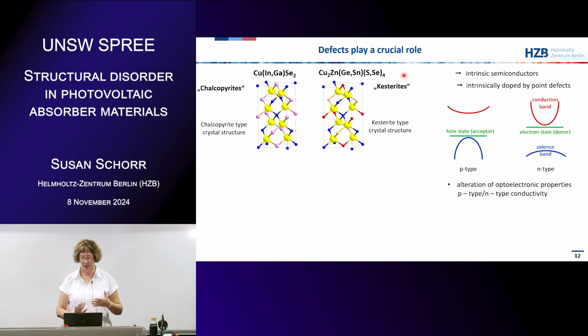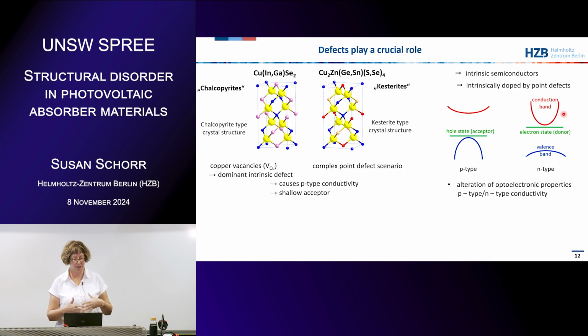So what that means is that due to the point defects, we have energy levels in the band gap. So this is the valence band and the conduction band, and in the band gap you can have levels. If it is closer to the valence band, then it's an acceptor level, and if it's closer to the conduction band, then you have a donor level. And that's why the material becomes N-type or P-type conducting. So in these compound semiconductors, chalcopyrites and kesterites, the dominant intrinsic defect which causes the P-type conductivity is said to be the copper vacancy. And it's a shallow acceptor.